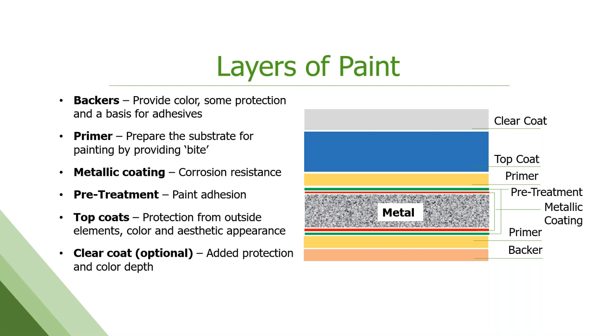Then you may have a clear coat on the exterior side, maybe not. The backside of the strip, even though it's not necessarily going to be exposed in the final application, is also coated with primer and what we call a backer coat or a bottom side coat. We do that for a couple of reasons. One, for protection of the surface and corrosion protection as well. But when you wrap this product back up in coil form, if one side is still metal and the other side is painted, it's very prone to marring and scratching that painted surface. The bare uncoated side will leave defects and damage on the coated side. So we always want to make sure that there's a coating on both sides when we recoil it back up.